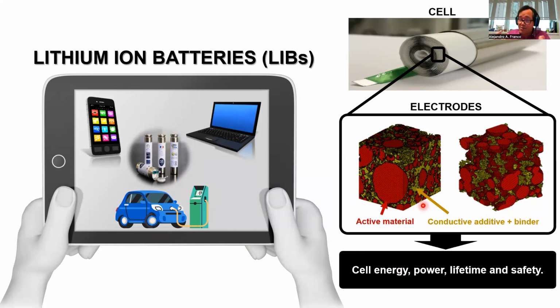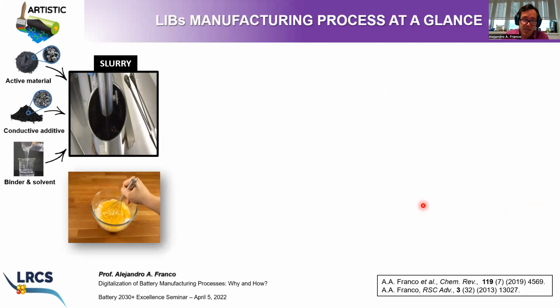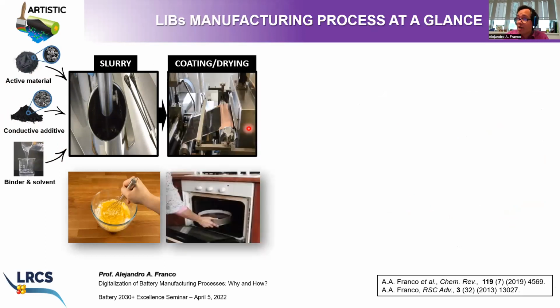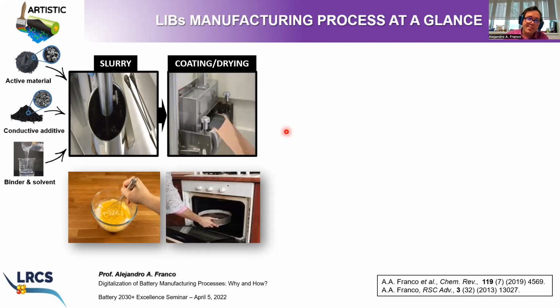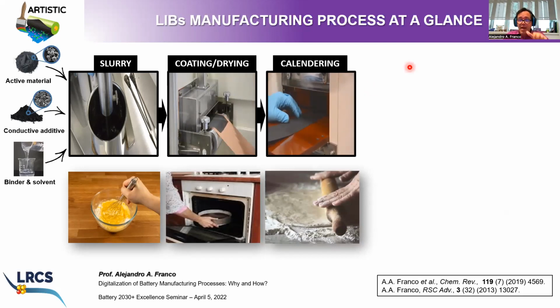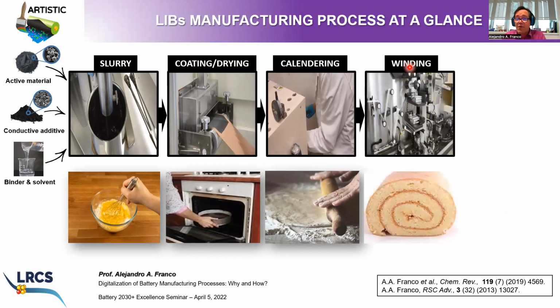In order to control the interfaces between these materials, of course, we need to talk about how we manufacture these electrodes. The manufacturing process of lithium-ion battery electrodes is highly complex. It involves multiple steps and multiple parameters. First of all, we mix the active material, the carbon additive, and the binder in a solvent. We prepare the so-called slurry. Then we cast the slurry on a current collector to prepare the first electrode of this lithium-ion battery cell. We pass the resulting coating through an oven in order to evaporate the solvent, and then we get the dry electrode. Then we perform the calendering, which consists of applying a pressure on top of the electrode in order to improve the electronic contact between the particles. And then we perform the same thing for the second electrode.